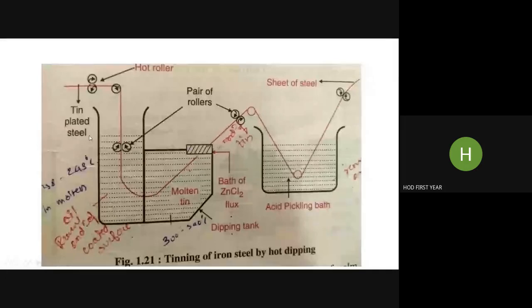Okay, so here we have a steel sheet to be coated with tin. First the cleaning process, so first acid treatment, and then washing, that is not shown over here. Okay, then washing, then drying, etc. Okay, and then it is passed through the molten tin tank. So this is the molten tin tank, at something around 320 degrees Celsius temperature. Okay, and here we have a zinc chloride bath, zinc chloride flux, to avoid oxidation of tin.